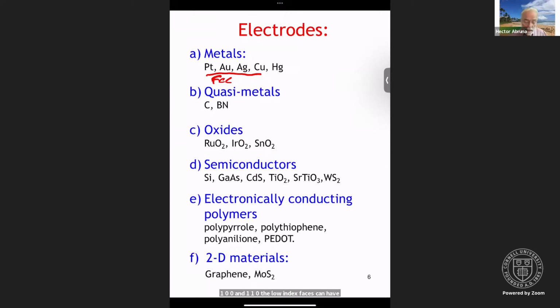I include mercury here because mercury for the longest time was the electrode choice. It has some limitations and some advantages. The limitation is that it oxidizes rather readily at relatively low potential, around 0.2 volts or so. However, it has a very, very broad negative range. And so it's used in a lot of reductions, even in aqueous media at very negative potentials. In fact, you can reduce sodium ions to sodium metal in water at a mercury electrode and make a so-called mercury amalgam.